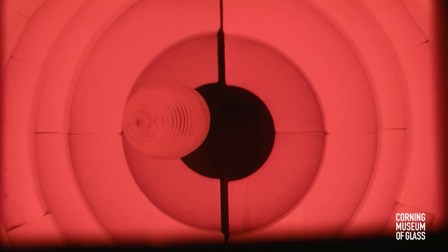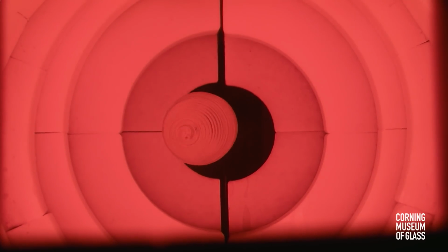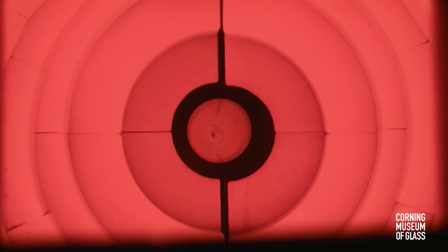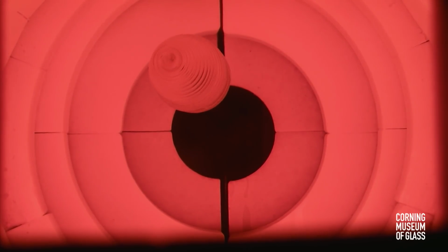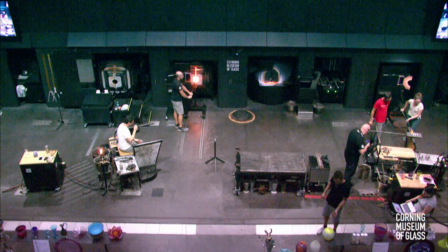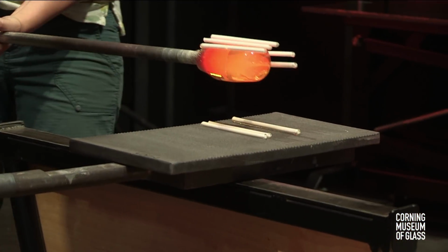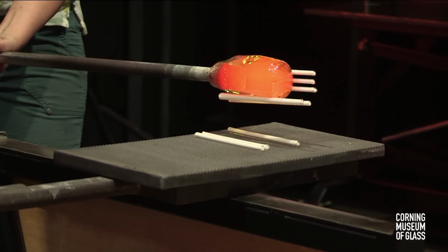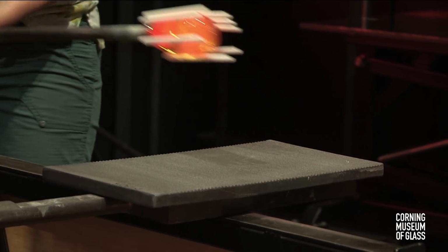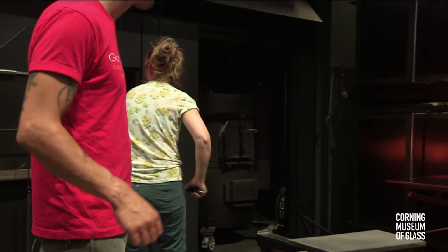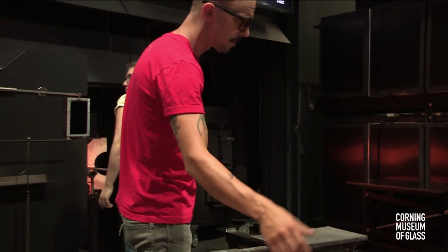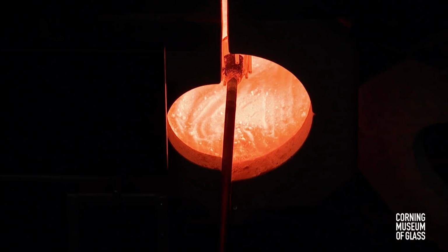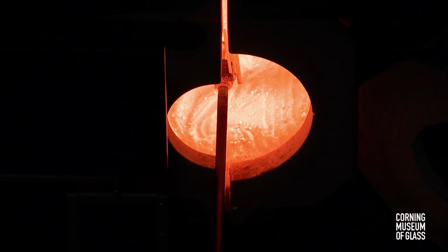When a good glassmaker marvers, this table is called a marver, so we call that act of rolling back and forth marvering. When a good glassmaker is marvering, they make it look so easy and effortless. Like you just set it down and then it just rolls itself. It is not the case at all. You really have to apply a lot of upwards pressure to stop that bubble from flattening. Because if you come over to the table and just set it down, even for a split second without rolling it nicely, then you're going to create a flat side on it. And then if you get a flat side on there, it's very hard to correct that. And you'll see him use the marver quite a bit for this piece, I'm sure.